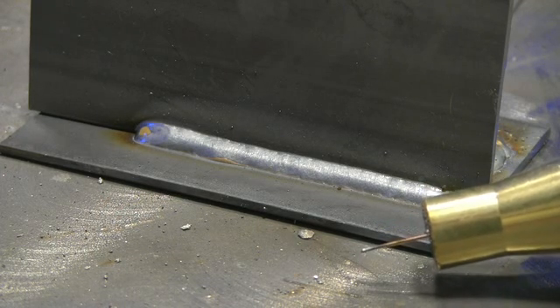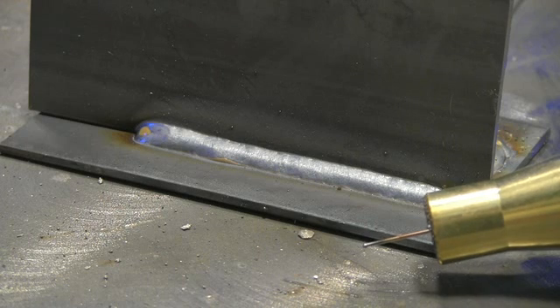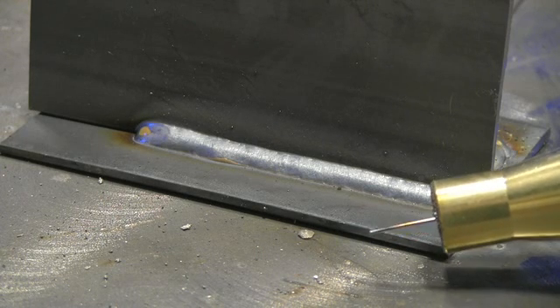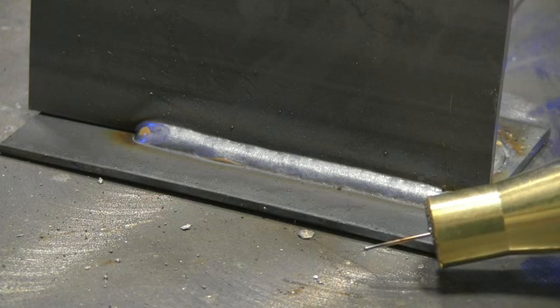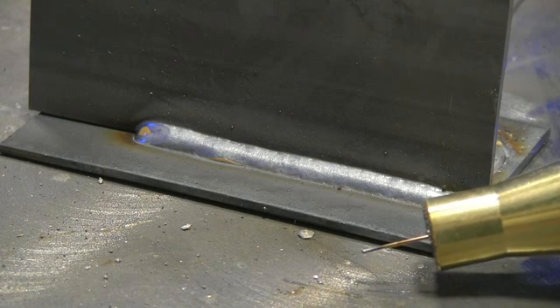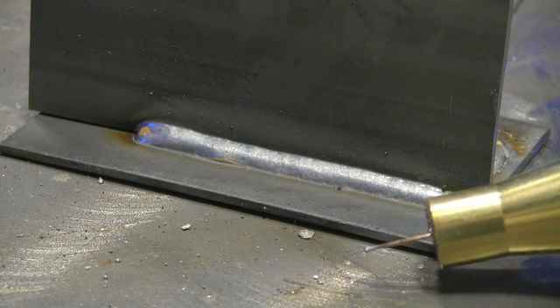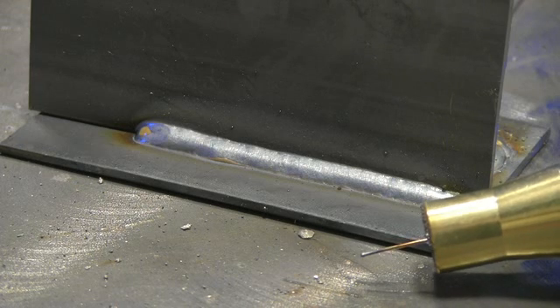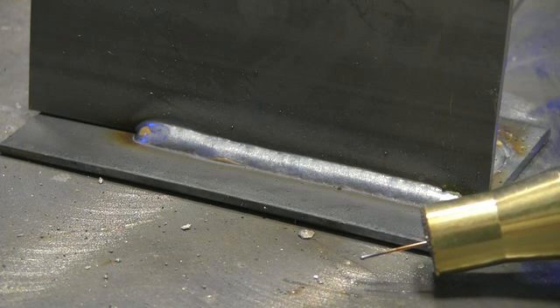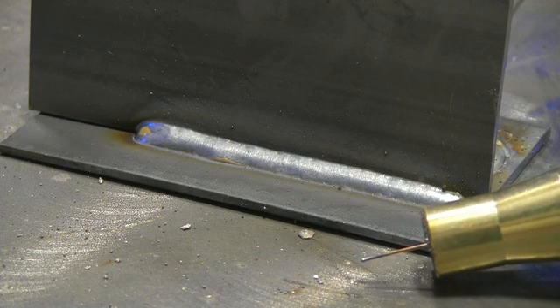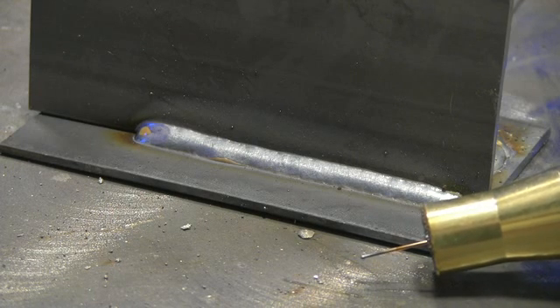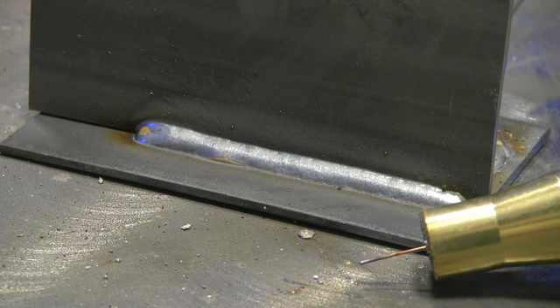Another good telltale sign if you were in a good stable short circuit transfer is the small ball at the end of the wire when you're done welding. Notice that the ball is about the size of the diameter of the wire, or maybe just slightly larger. This is a good indication that we were in short circuit transfer. If the ball is two or three times larger than the end of the wire, that's a good indication that you were not in short circuit and that you may have been in globular transfer. So everything right there looks very good and tells me that we're in a nice short circuit transfer.